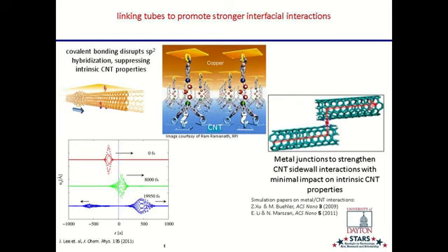This is a simulation. Actually, these simulations are just for one molecule on a long carbon nanotube. And you have the same thing happening here. You send a heat pulse in. You have reflection at just that site where the molecule is. So by functionalizing the carbon nanotube, you enhance its interface, but you ruin the properties of the carbon nanotube itself by breaking up those bonds.